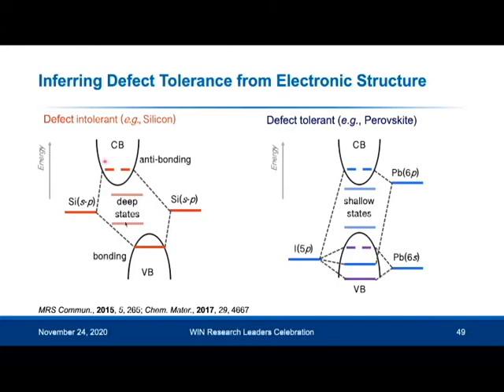So on the left-hand side, we have the structure for a traditional semiconductor like silicon or gallium arsenide. And in these materials, the atomic orbitals hybridize to form a bonding and anti-bonding orbital pair across the band gap. You then end up with the original atomic orbitals being close to the middle of the band gap. So when you break bonds and have defects, the defect states will form at energies close to the middle of the band gap.